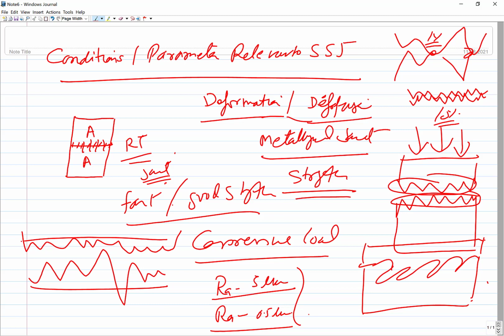But when you apply load, there can be a lot of difference in terms of the temperature conditions. Let's say when you apply a load of 5 MPa at room temperature, RT, nothing will happen. But when the same load, leading to 5 MPa pressure, is applied at 500 degrees centigrade, the metal will lose its yield strength. All peaks and valleys will collapse very easily. They will come closer. All voids will be broken. Voids will be closed. So a firm metal to metal contact will exist.